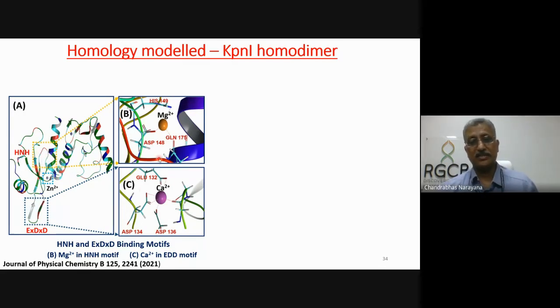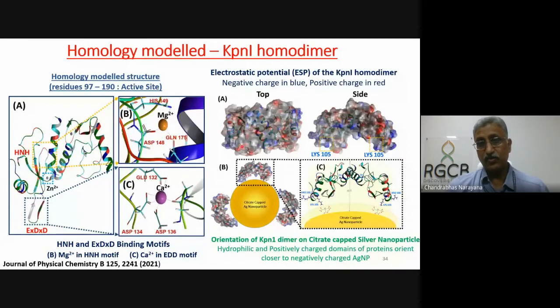So this is the situation, and we could see where it binds in the system. With this in hand, we could look at the charge, because we wanted to understand how it goes and sits on top of the nanoparticle. If you look at the charge, we see that around this region there are two reasons for it to attach. And by the way, this protein exists in a dimeric form. That means it is not one protein. It is two proteins coming together, making a protein which is viable. This is the dimerization. You can see there is a lysine group sitting here. That is the anchoring point, and this is the region where most of the positive charges are. So this is how it would be sitting on the nanoparticles.